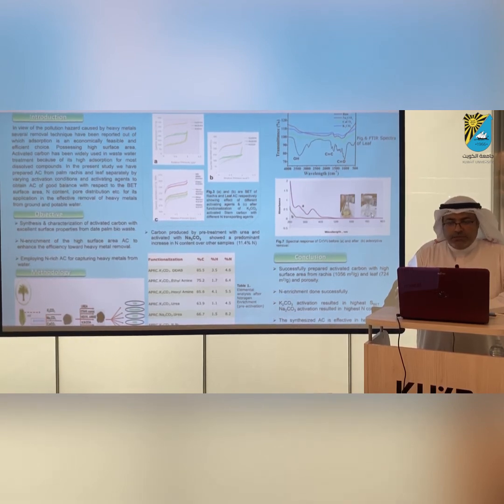And now in the future we want to reduce the energy consumption in this process, because although our material is a waste material, so it's green chemistry, there is also consumption of energy during the pyrolysis of the plant. Pyrolysis usually takes several hours, because you have to heat the material up to 600 or 800 degrees. Gradually, this will take maybe 1 or 2 hours, and the cooling will take several hours also. So we want to reduce the time and the energy consumption.